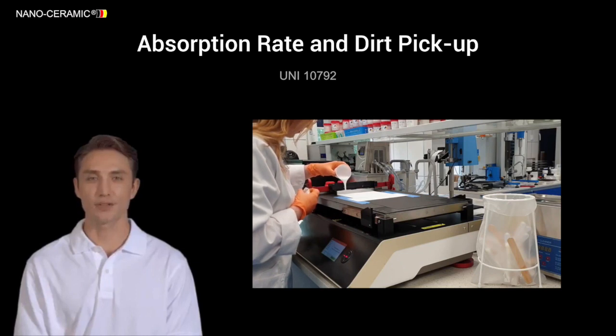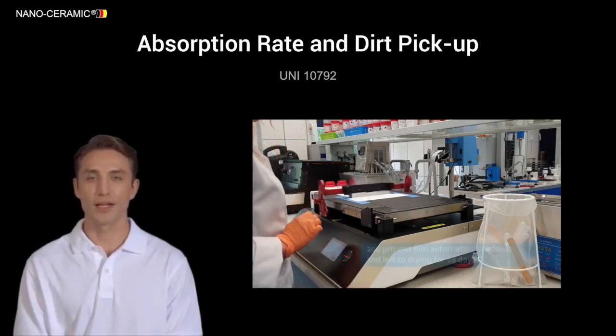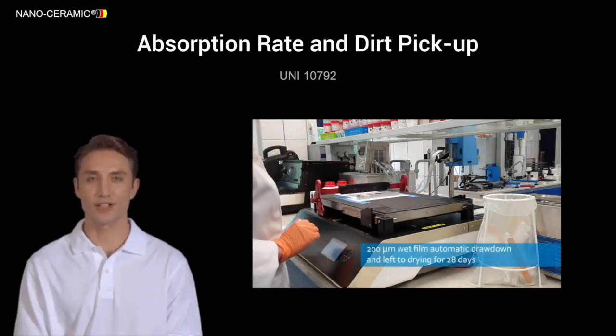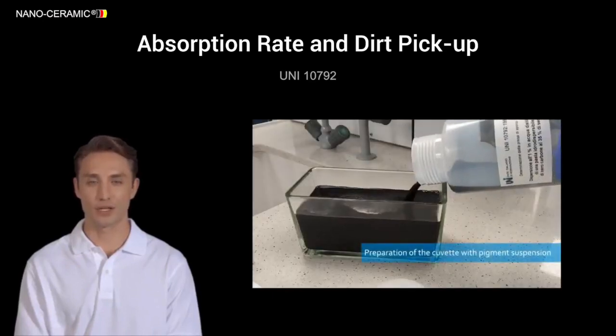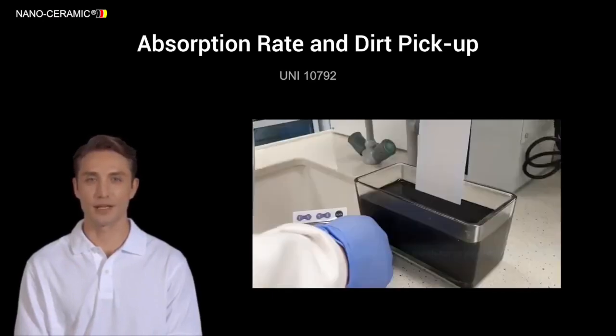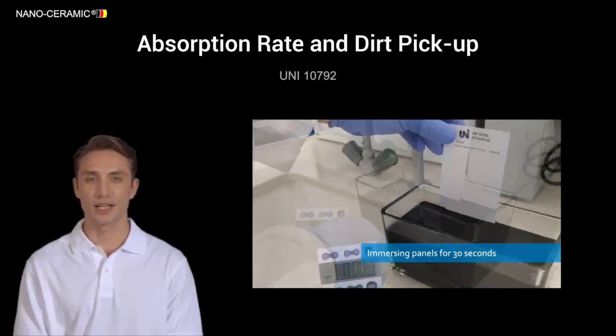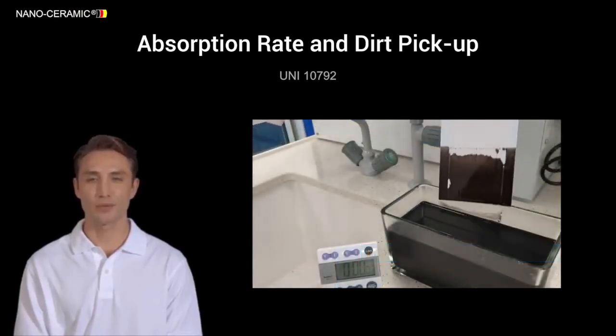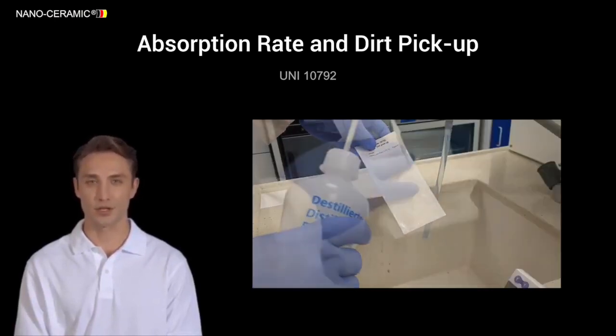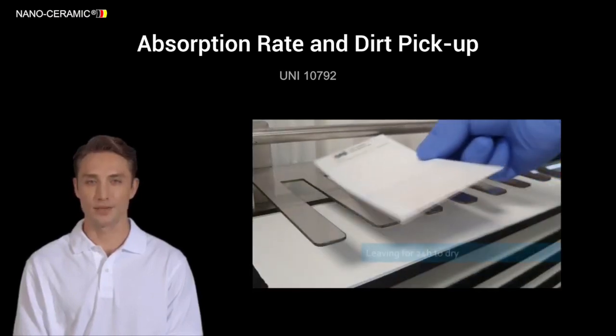This is to make sure that no water and dirt can enter into the paint layer. Almost all conventional paints have an absorption rate between 1 and 3%. In the movie next to me you see a latex paint that is tested with a rate of less than 1% absorption. You can clearly see that dirt does not penetrate into the paint layer.